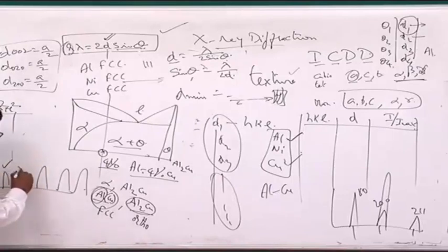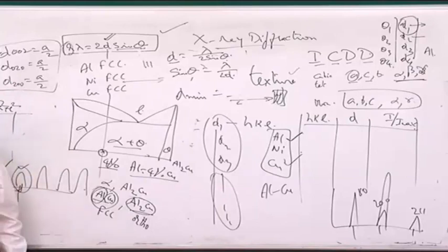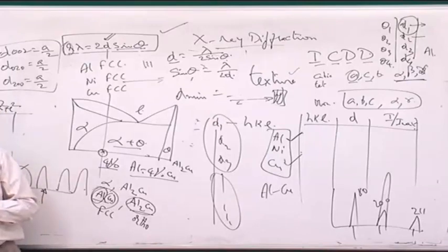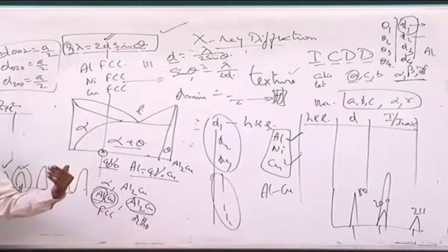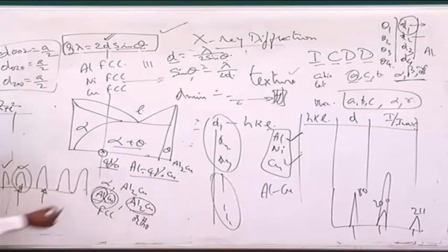Then I go to the second peak, and then look at those 100 once again and see which of those 100 do not have a peak at this position. Eliminate all of them. Now some 10 are left out. Now go to the third and see which out of the 10 will have the third one also. And then like that I go one by one, and by the elimination technique I will be able to find out that this material is composed of these things. So like that I have to do.